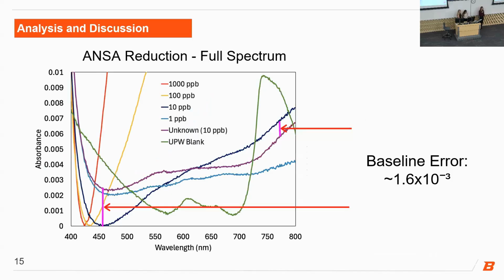So then we looked further into sources of error, and we realized that we have a significant variation in our baseline measurements that we weren't expecting to see. The baseline variation was about 1.6 × 10⁻³. And this is over 50% of the signal that we should have been getting for the 10 part per billion sample. So this would, in theory, impact our ability to detect that low of a concentration.